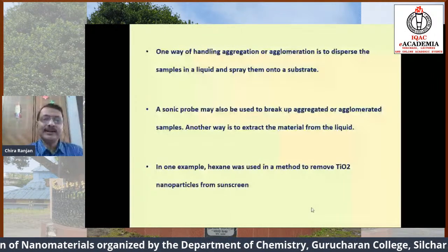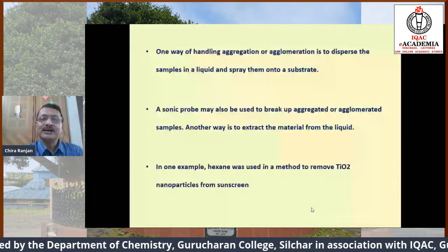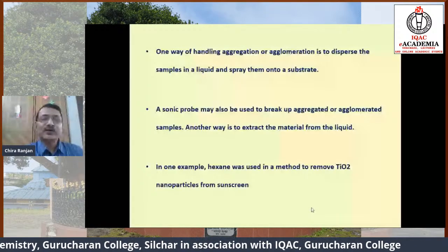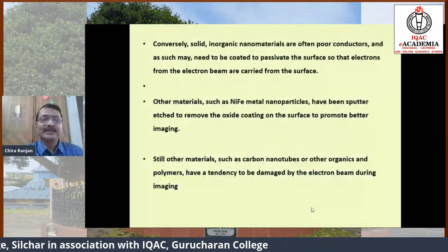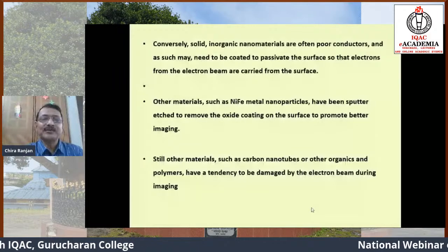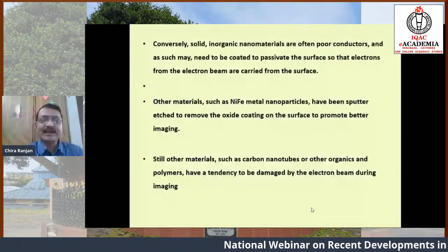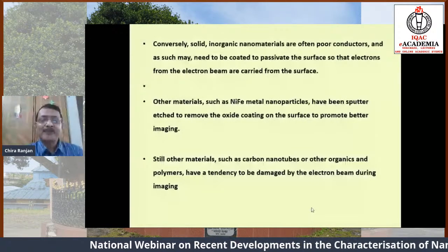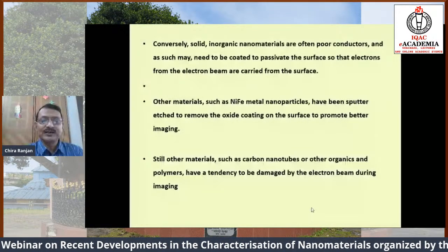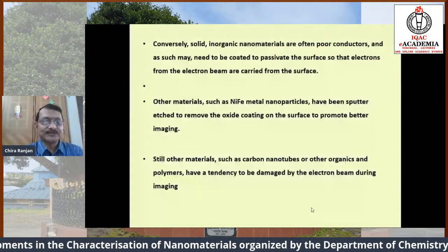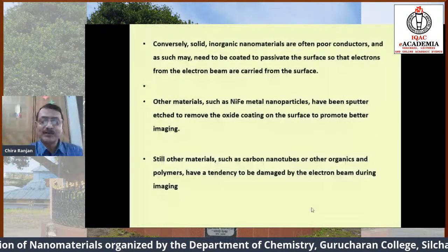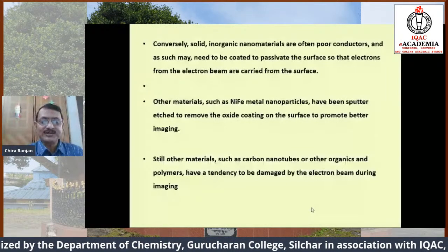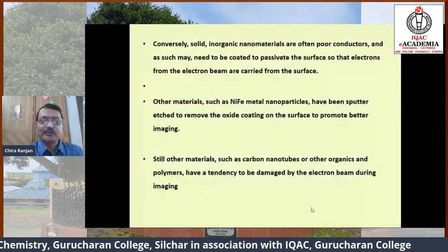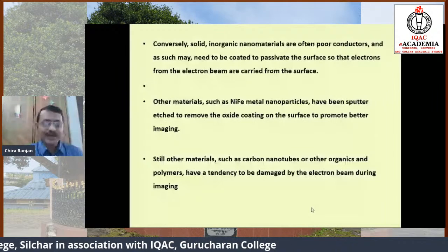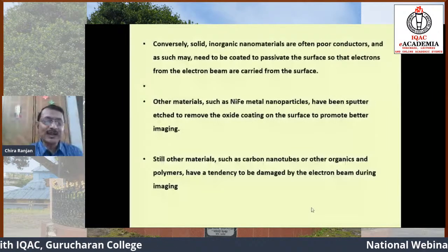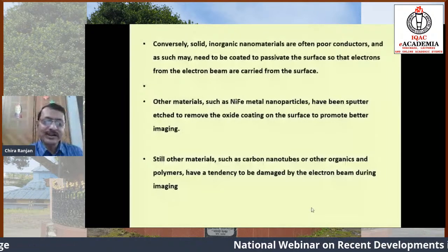Conversely, solid inorganic nanomaterials are often poor conductors, and as such may need to be coated to passivate the surface so that electrons from the electron beam are carried away from the surface. Other materials such as NiFe metal nanoparticles have been sputter etched to remove the oxide coating on the surface to promote better imaging. Still other materials such as carbon nanotubes or other organics and polymers have a tendency to be damaged by the electron beam during imaging. So we need to adopt some special care when we try to image carbon nanomaterials or organic nanomaterials.